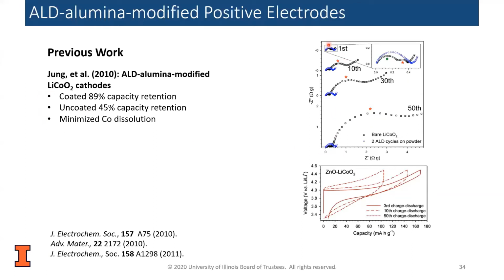And you can see here the differences in impedance with the cycling. So the bare are these little dots, and the uncoated, well, the bare is this one, and the coated are these, excuse me, the blue is the coated. And you see there's not a lot of increase in the impedance.